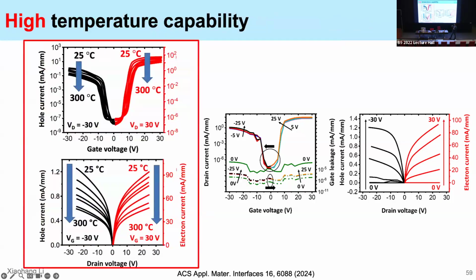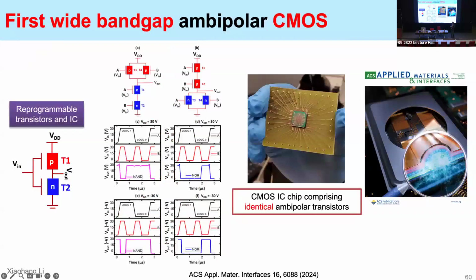As I mentioned, what we want to use it for is extreme temperatures. So we actually measured the transistor anywhere from 25 degrees to 300 degrees Celsius. As you can see here, the transistor actually operates very stably at those temperatures. We didn't go to even higher temperatures because our probe station is limited to 300 degrees C. However, I believe that this transistor can operate at even higher temperatures. Based on this transistor, we demonstrate the first wide bandgap ambipolar CMOS. So those are, again, programmable transistors and ICs. And this is just a simple demonstration of the basic logic gates like the NOR and NAND.